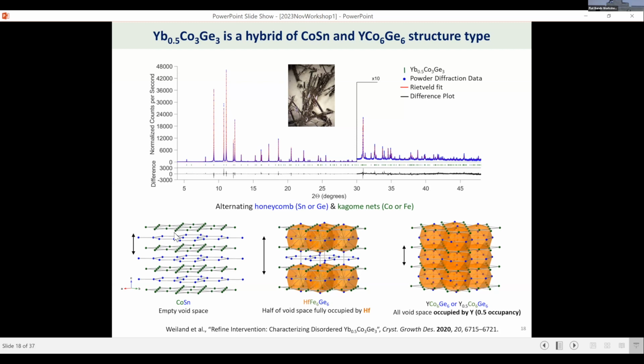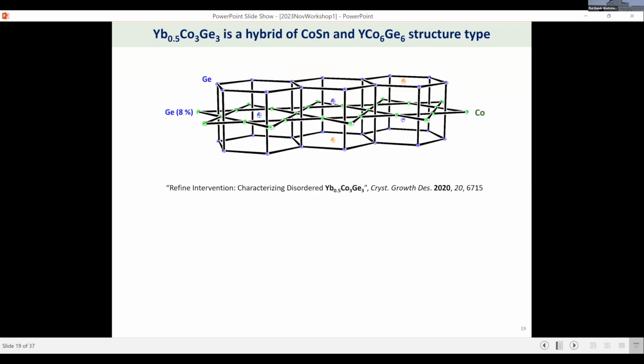Now I have to admit that I decided to hide one of the cobalt sites along the Kagome nets, just for clarity, but they do exist. Nonetheless, this has been a lot of fun because now we are able to say that this hybrid structure is not 166, it's not cobalt tin, but it is a hybrid in the sense that here we have the rare earth occupying along the Kagome nets and also along the hexagons. So let me show you what this would look like.